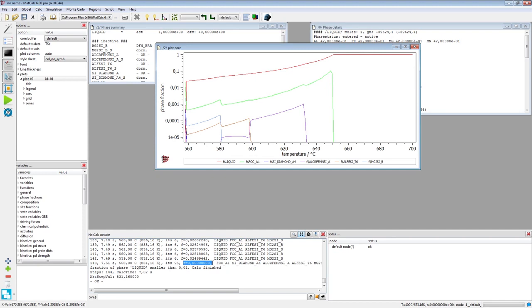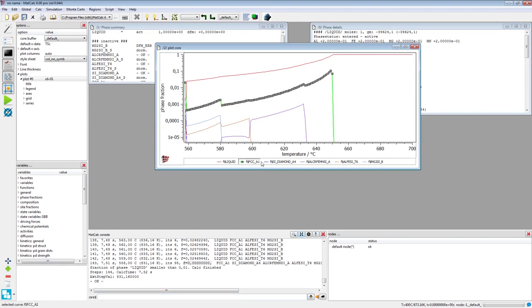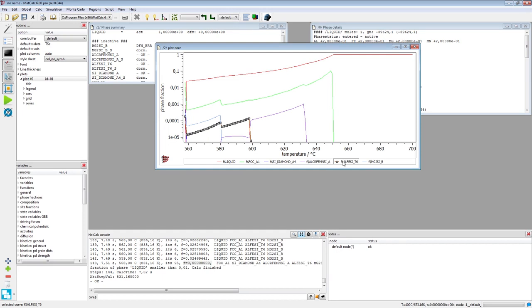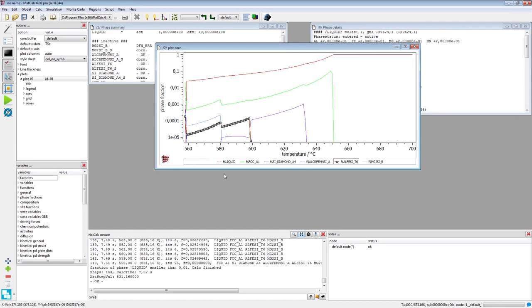Moreover, the content of the phase fraction plot was also changed. The phase fraction curves show now the amounts of the phases solidifying at the given temperature. It can be noticed at this point that the beta intermetallic phase is also expected to form during the solidification, even though it is not an equilibrium phase.